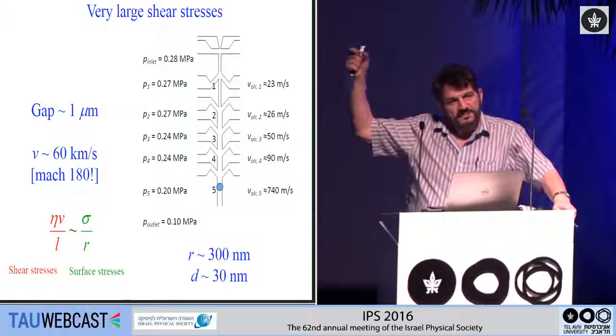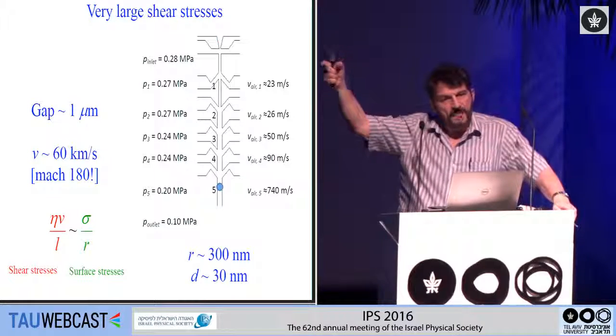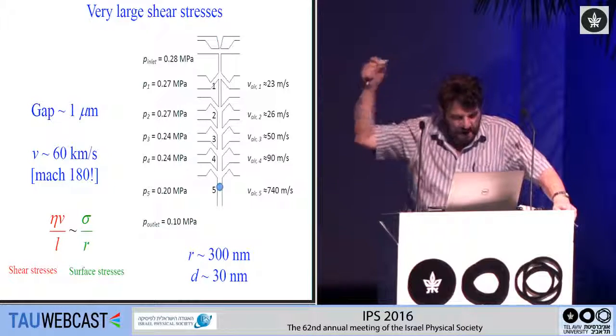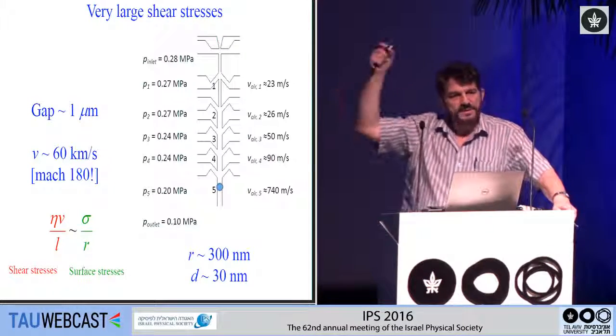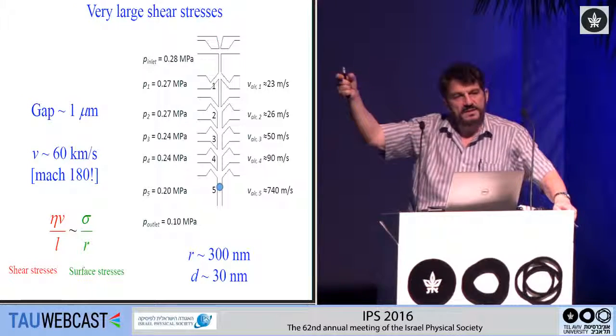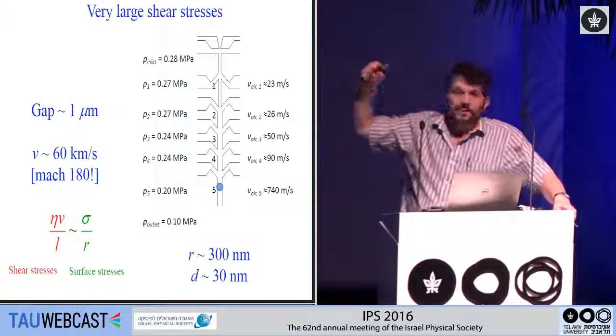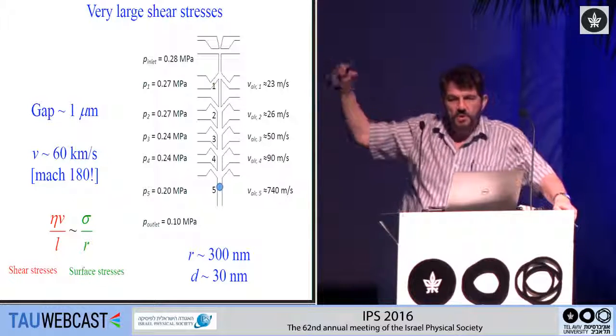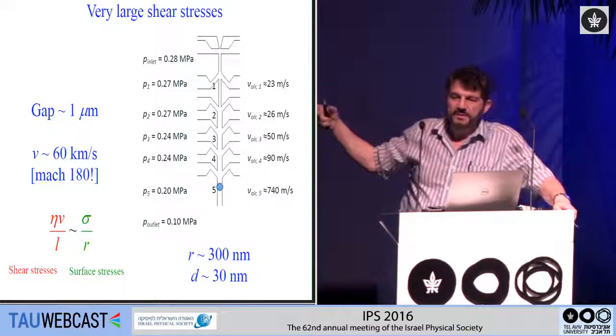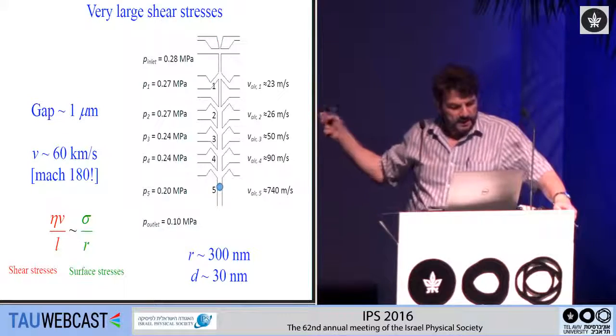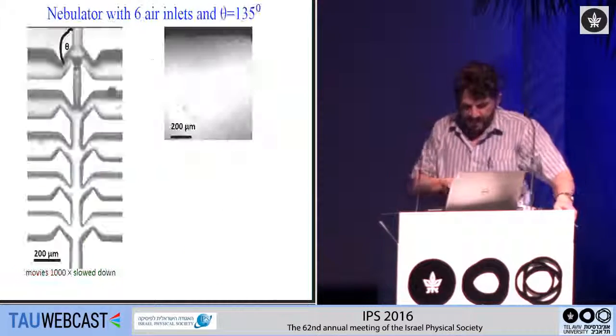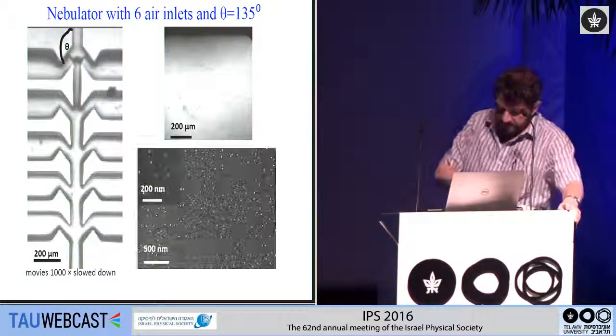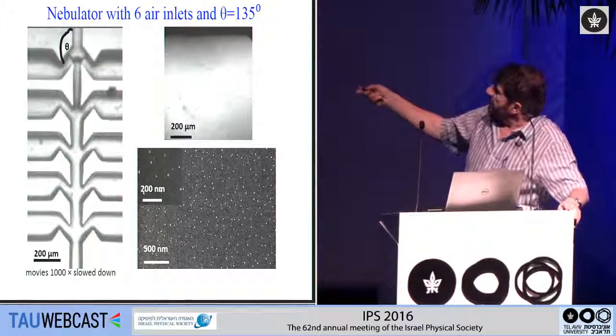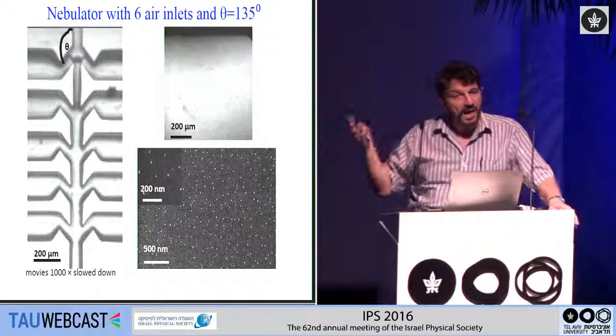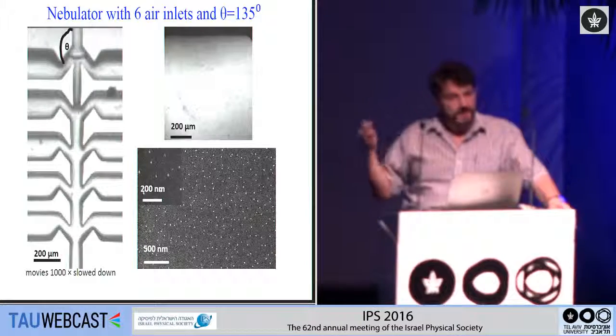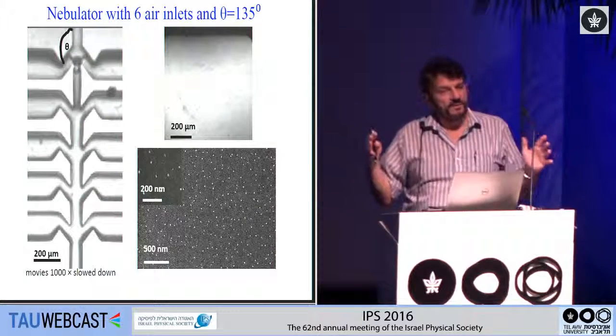And then I can ask, if I put some particle or some solute inside the solvent, if I put something that will precipitate inside the solvent, I know the concentration. So I'm going to show you cases where I put a known concentration. What's the size of the particles that I'm going to get? It's something like 30 nanometers. And if you look, this is just looking at the outlet, if you look, that's exactly what you get. You get tiny, tiny particles. You get nanoparticles, and now these are very, very uniform.